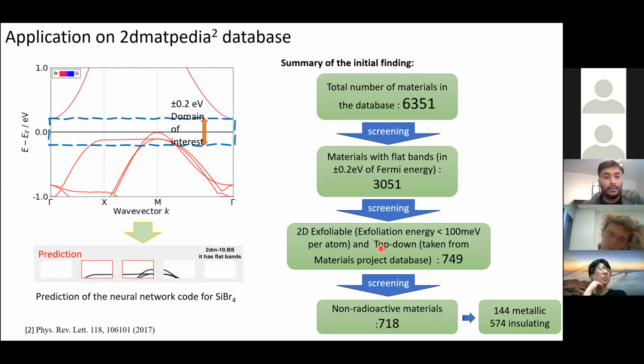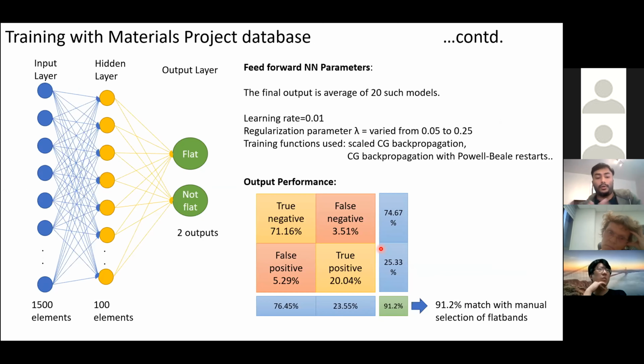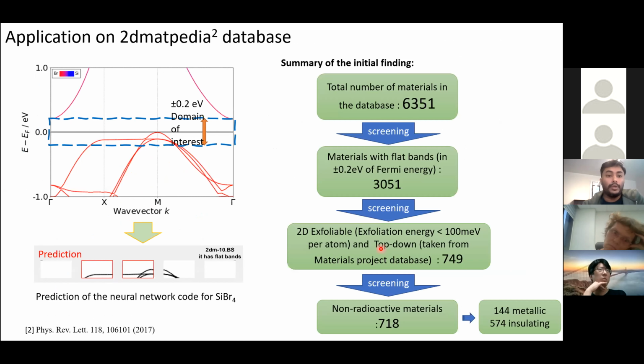I'll show you. So after this, we have got a neural network model now which can predict flat bands. Now we have tried to identify 2D materials with flat bands, and we use the 2D Materials Encyclopedia database. We took a domain of around 0.2 electron volts around the Fermi energy. And this shows a prediction like this, where the flat band segments are highlighted. If any segment is highlighted, we can call that material to have a flat band.